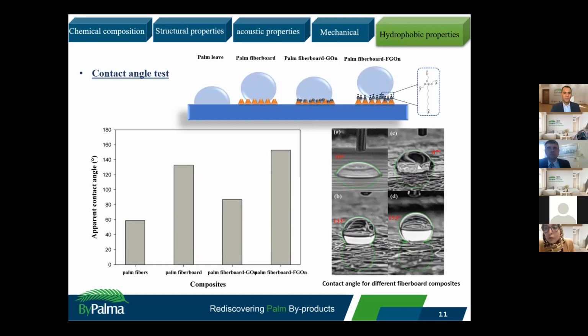This figure shows a typical image of a water drop on the composite, and as you see, the palm leaves, which is in figure A, are in general hydrophilic with a contact angle of 59 degrees. For the combination of palm fiber and epoxy binder as a reference, the fiberboard panel showed a contact angle value of 133 degrees due to the rough surface of the composites, of course.